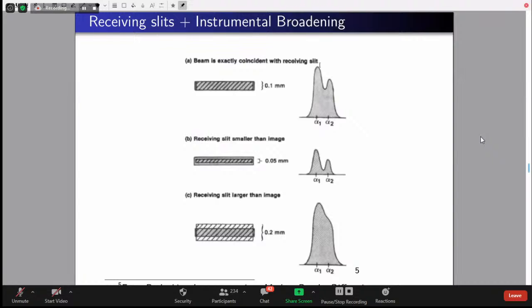We can see those things. So this is the receiving slit, and I am giving here the size, how much it has been opened. This is 0.1, here 0.05 and 0.2. You can see the resolution. In the first case, the resolution is poor but you have large intensity. If you want a good resolution, it is available at 0.05, but you lose the intensity. If you open it wide, you have good intensity, but you lose the resolution. Means alpha 1, alpha 2. Here we are talking about only one peak, but if you take anything hexagonal, let us suppose zinc oxide, at very low angles between 20 and 30, we will have a triple peak in zinc oxide.